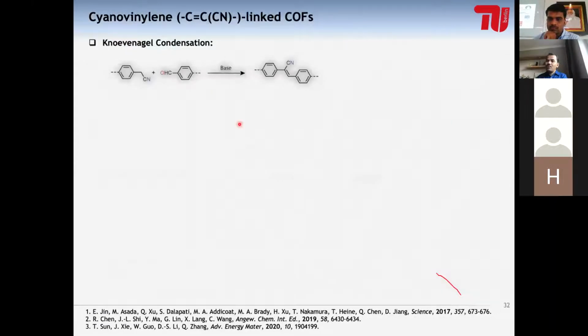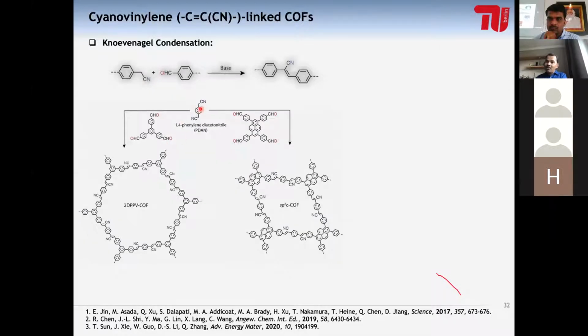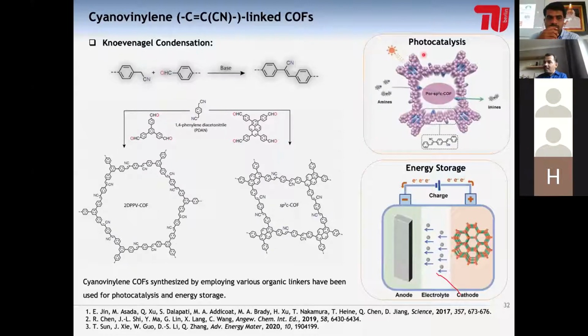To do that, we have chosen the Knoevenagel condensation reaction, where taking the advantage of active CH2 groups in these kinds of linkers, we can synthesize COFs composed of just carbon-carbon double bonds. And there is no labile bond now, which cannot be reacted during this whole process. Most importantly, these materials showed improved photocatalysis and energy storage properties as compared to their counterparts like imine-based COF as well as boronic acid COF, which is pretty nice.